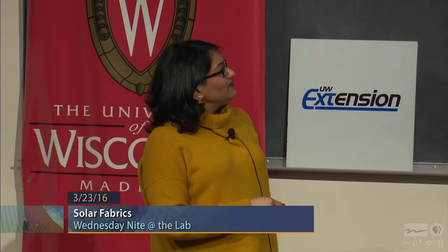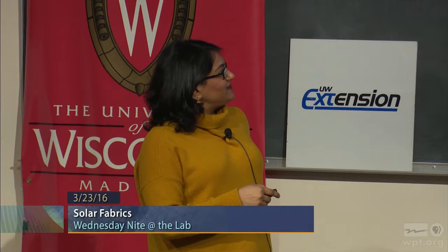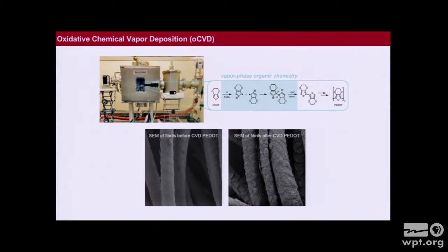So here is, again, another SEM of, I believe, cotton. I'm not sure, but it doesn't quite matter. This is a collection of fibrils of cotton, let's say, before deposition. And then this is the same sample, different set of fibers. I can't quite say it's the same, but it's the same sample after deposition of PEDOT under the vacuum. And what you see is you get a little bit of roughness. That's because we have our PEDOT deposited on the surface.